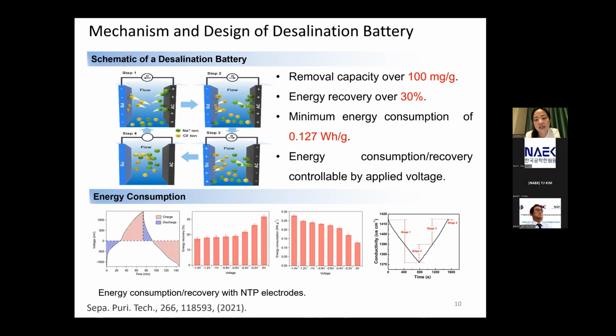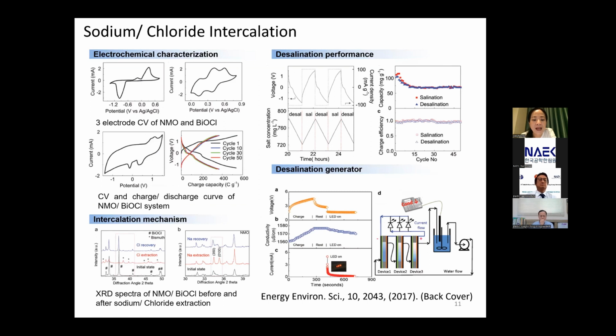The minimum energy consumption for this structure is very low. In fact, we can treat the seawater at 0.127 watt-hour per gram, and the energy consumption and recovery rate can all be controlled by the applied voltage. We also designed sodium and chloride intercalation electrodes using NMO and bismuth oxide chloride. Both structures have demonstrated intercalation behavior for sodium and chloride.